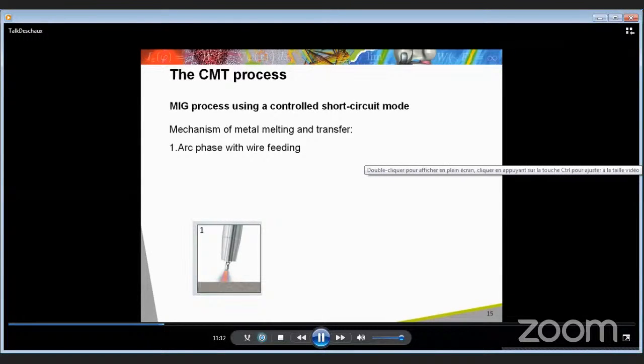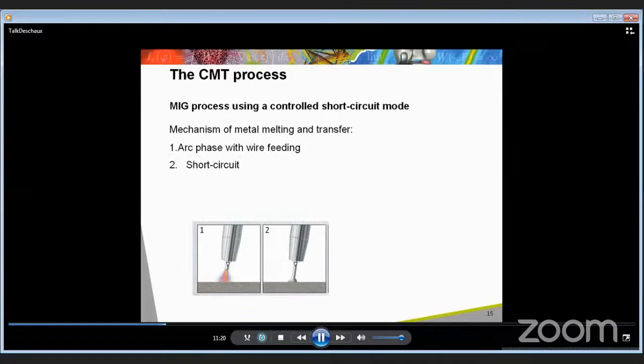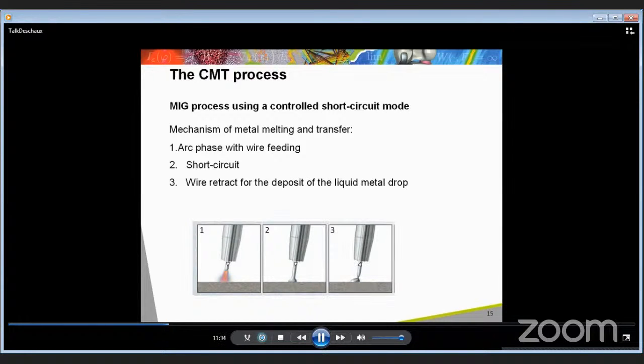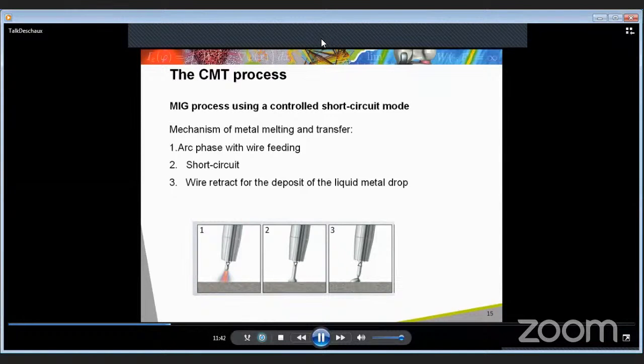In the first step of the cycle, the arc melts the wire tip and the wire is fed towards the workpiece. Then, the liquid drop formed at the wire tip enters in contact with the workpiece surface, producing a short circuit on the arc extension. In the third step, the wire is retracted up to its separation from the workpiece, leaving the drop of liquid metal deposited to solidify on the workpiece. Finally, the electric arc is reignited and a new cycle begins.